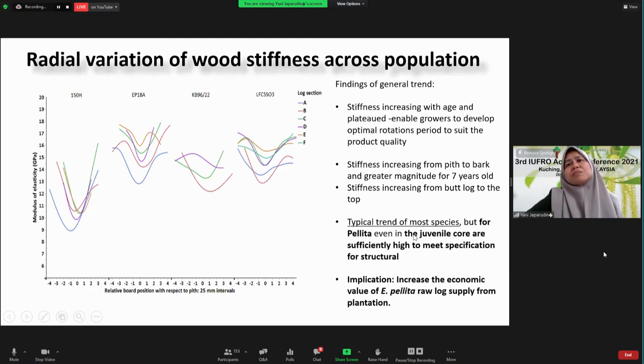And actually this is a typical trend of most species being studied by many researchers. But for pellita, even the juvenile core is sufficiently high to meet specification for structural use. So we can see the 7 years old stand here, the lowest near the pith, the MOE value is about 9. So what is the implication? This information will tell that it increases the economic value of Eucalyptus pellita raw log supply from plantation.